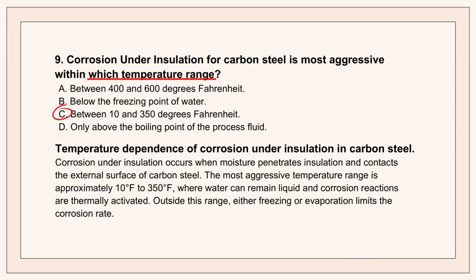Well, below freezing, corrosion pretty much stops. Not enough liquid water. At very high temperatures, say above 350 Fahrenheit, any water that gets in just flashes off as steam. So the water can't stick around. Right. But that 10 to 350 range is the sweet spot. It allows liquid water from rain, leaks, condensation to stay present for long periods of time while still providing enough thermal energy to constantly accelerate the corrosion. And it's hidden under the insulation. Hidden the whole time. It often goes undetected until you have catastrophic wall thinning.